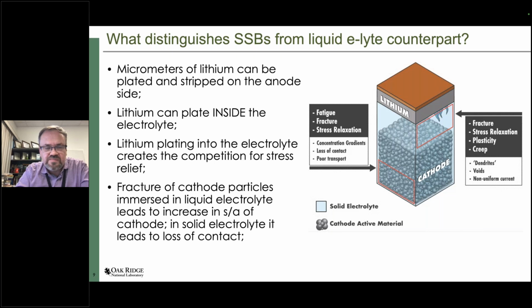Number 1 is that in liquid electrolyte, lithium can plate only on the surface of the anode. If it's graphite, it will always plate on the surface of graphite. So that gives you at least some degree of control over where to expect your lithium to appear. In the case of solid-state batteries, it can plate inside the electrolyte, which is especially pronounced in garnets. It can just start plating in the bulk of the electrolyte. And the strain in the cathode particles can lead to the fracture of those particles, and in liquid electrolyte, that just leads to an increase of the surface area. In the case of the solid electrolyte, that leads to complete loss of contact between the electrolyte and the cathode particles.